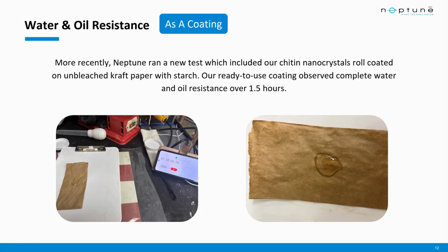So of course, I can't release too much data just yet, but I can definitely give everyone a quick sneak peek. Now, as they say, a picture's worth 1,000 words. As you can see here, a typical kraft paper, untreated, naturally existing, once it's coated with our chitin nanocrystal, it was able to withstand water penetration for more than an hour and a half. And the droplet of water, if you really zoom in, is still perfectly beaded, and there's no sign of any absorption or penetration.